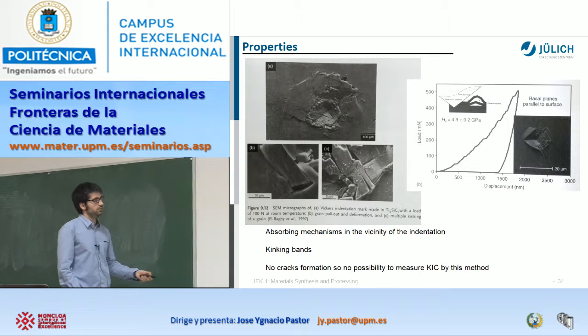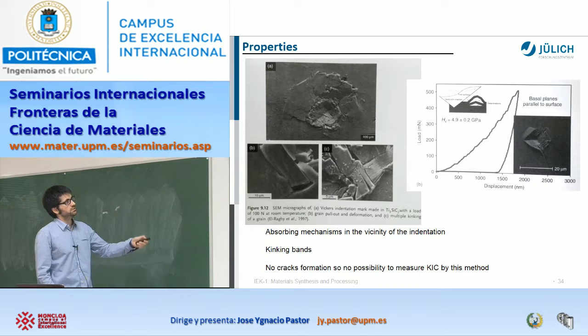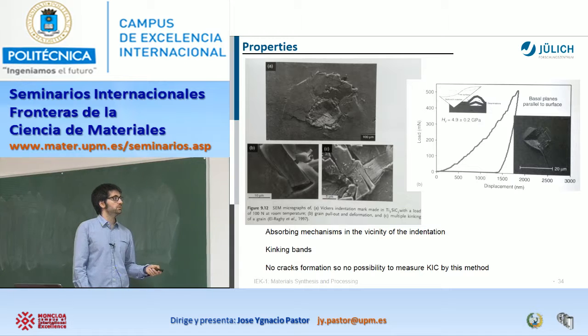You absorb all the energy through mechanisms in the vicinity of your indentation, and this is a quite interesting response of the material that would be great to study further at high temperature. But okay, fortunately, there are not many studies. But this lack of cracks is a really good result.